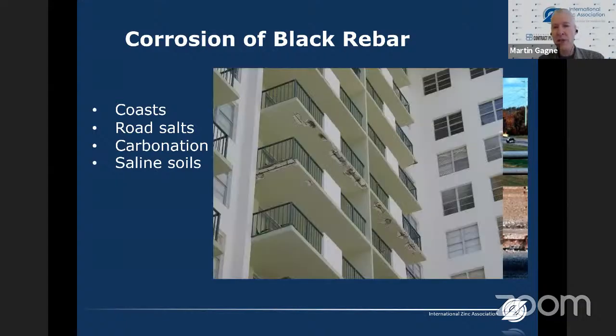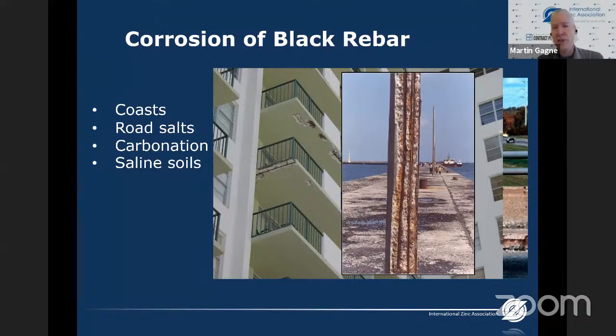And it's not just for highway structures. There was just a fatal collapse of an apartment building in the state of Florida in the United States. Corrosion has been blamed for the cause of that. Here we see some balcony structures with spalling concrete because of rusting reinforcing steel. This is a liability hazard. And of course, for coastal structures, any pier structures or anything near the coast, the chloride exposure is quite high, which leads to corrosion of the rebar, building up stress inside the concrete, which causes spalling, exposing more rebar and accelerating the whole process.